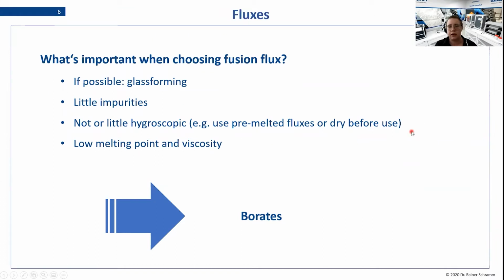Another very important point is that the flux shall not be hygroscopic, or just slightly hygroscopic. This you can achieve by using pre-melted fluxes, or you have to dry them before every use. Why is that so important? When there's water inside your flux and you use it in fusion, the water will go away and you will have different dilutions with every preparation. And this will result in poor precision.